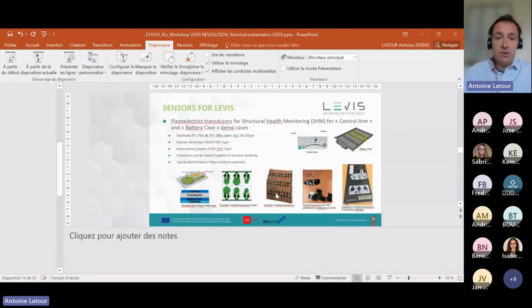We print polymer electrodes, which are made of PEDOT:PSS, very thin, non-metallic electrodes. We use, as mentioned before, an electroactive polymer made of PVDF-TrFE, which is a copolymer. And in order to increase the sensitivity or the performance of the actuator, we can stack different piezoelectric layers by printing them on top of each other. The typical stack thickness is between 10 and 50 micrometers without the substrate. You can see here some examples of the architecture we are using.